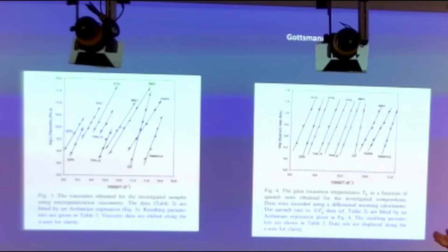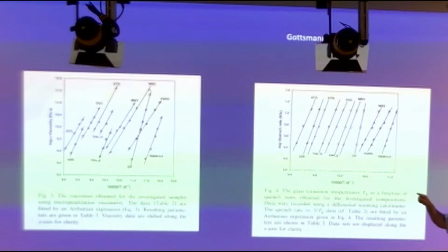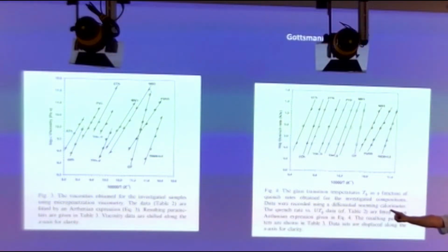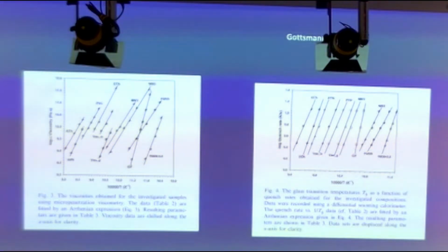So what we're looking at is the same phenomenon of relaxation in the liquid, but we're looking at it with a viscometer and we're looking at it with a calorimeter. It means that if you have a calorimetric measurement, you can state a viscosity. And if you have a viscosity measurement, you can actually state a calorimetric response. That was something that nobody liked when we said it in the early 90s. Although the glass scientists knew it, everybody in geoscience said we were crazy.